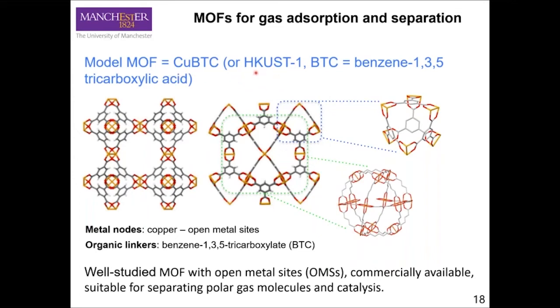The material I'm working with is CuBTC, or HKUST-1, developed by the Hong Kong University of Science and Technology. It's quite an interesting MOF. They have copper connected by benzene-1,3,5-tricarboxylic acid, which gives this highly porous structure. You have a copper dimer over here. Most importantly, this HKUST-1 MOF is commercially available. I think in Belfast there is a company that uses a dry method to produce it, and it's reasonably cheap now. Therefore, I decided to work on these materials.